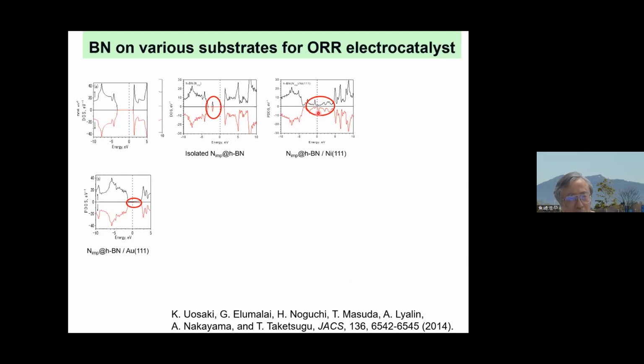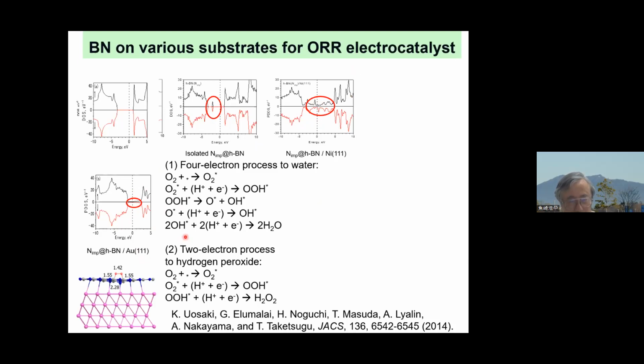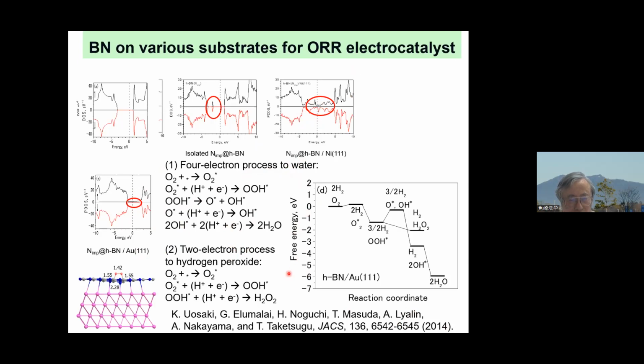If we calculated gold for this energy gap, compared with nickel, the density of states is relatively small, but still there's a possibility. We also calculated the free energy for the 4-electron process to water or the 2-electron process to hydrogen peroxide. This is the reaction coordinate and free energy change starting from oxygen to water. In this case, there's an uphill state, but in the case of hydrogen peroxide formation, a relatively smooth reaction is expected. So although it's not the final goal, still there's a possibility.